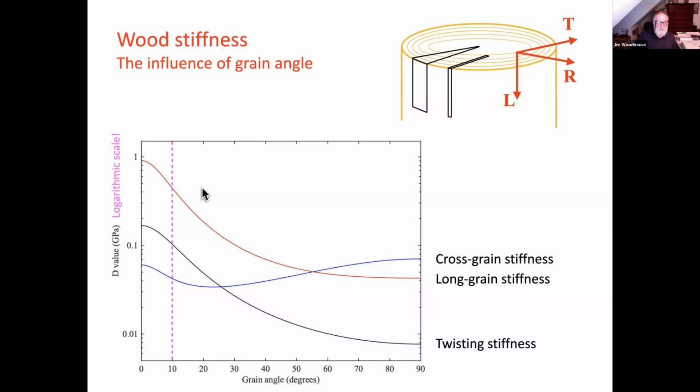By the time you've carved an arch through this, then on the falling slopes of the arch, you can easily get 10 degrees and more. And so it might matter for the details of the vibration behavior that the local stiffness on the slopes of the arch may be significantly lower than it is in the middle of the plate, where you're nicely aligned along the split direction.